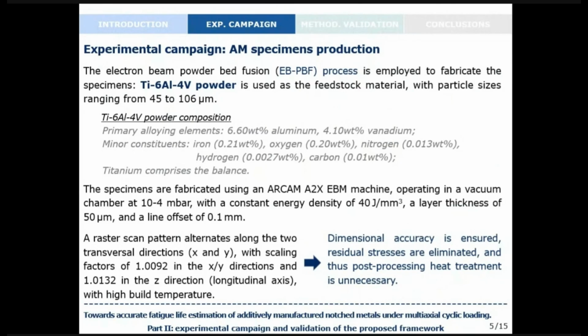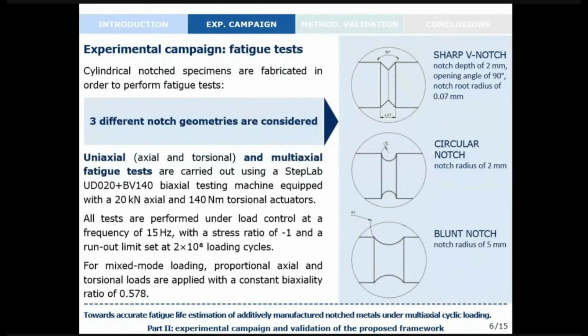And let me say that with these process parameters and with the high build temperature, a high dimensional accuracy is ensured, the residual stresses are eliminated, and so we didn't need any post-processing heat treatment on the specimens. So, first of all, fatigue tests have been performed on cylindrical notched specimens.